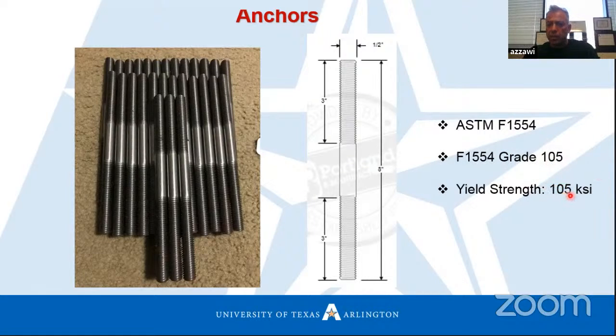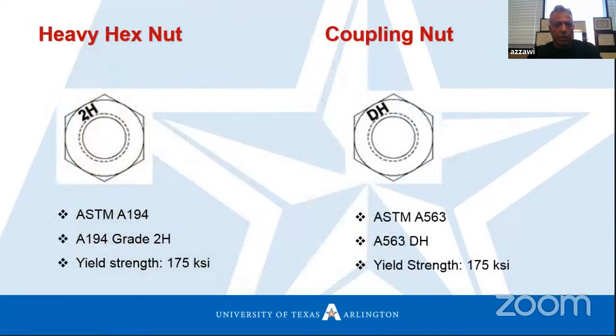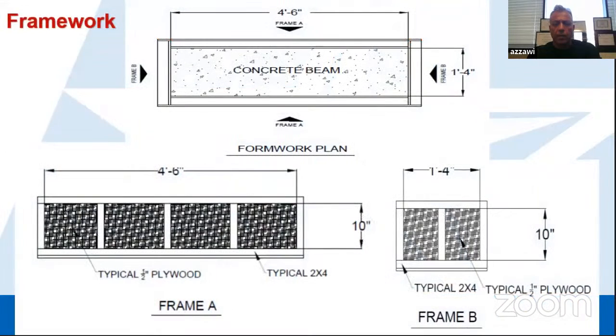I use this yield strength just to make sure I don't have any yield failure in the steel itself. I need the failure to be developed in the concrete itself. So we use 0.5 inches diameter with 9 inches length. Also, we ordered heavy hex nuts with coupling nuts, which is used in this research.